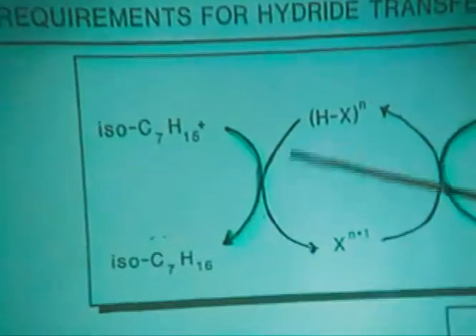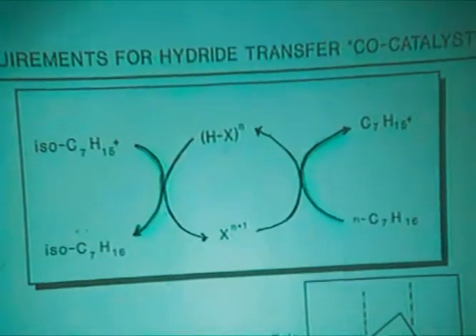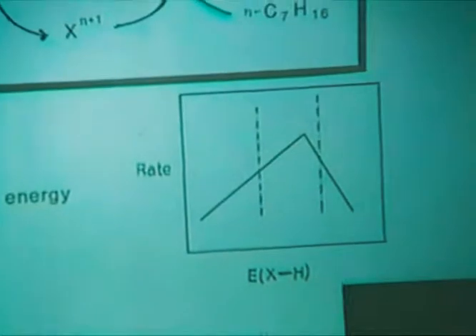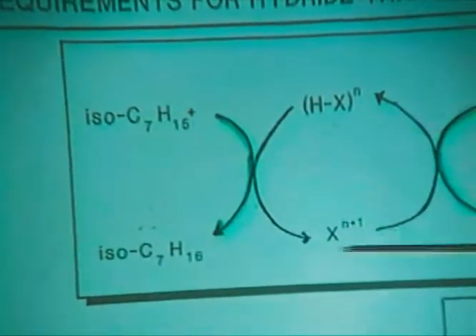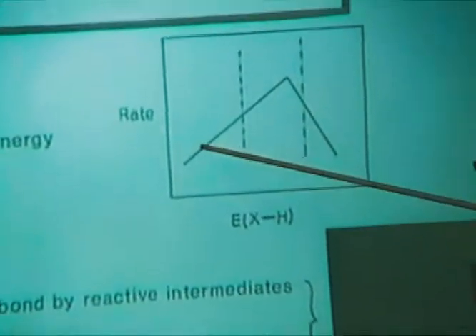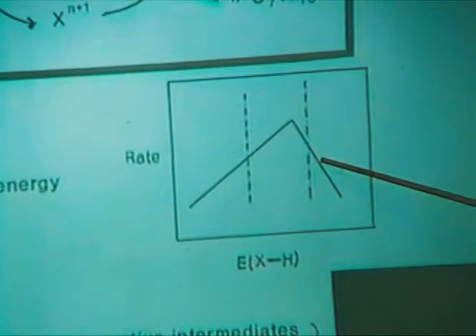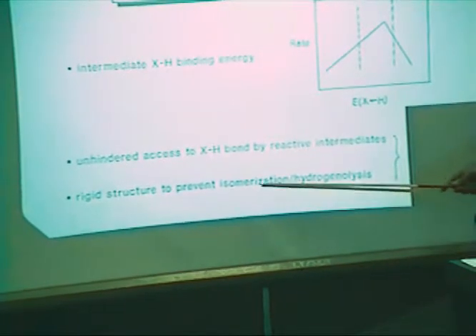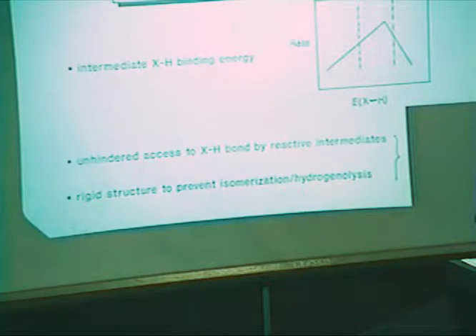This is usually a first order reaction in the alkane and a negative order reaction in hydrogen because of this equilibrium right here. This one is usually not. So if you look at what the kinetics actually look like, on alkane they're very low order, and on hydrogen they're actually positive order, and that's unusual in the sense that it does not resemble most of the high temperature bifunctional type reaction mechanisms. So now, if this is the case and I'm left with my challenge to increase the rate of the reaction, to decrease the residence time of that intermediate so that it doesn't crack, what I ought to be doing is looking at things that can do this more efficiently than what I have right now. And what I have right now are linear and isomeric alkanes sitting in that system. So with the help of someone at Exxon that had a great deal of experience in this area, we actually came up with one possible solution.